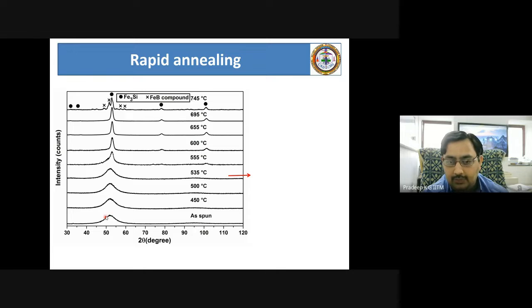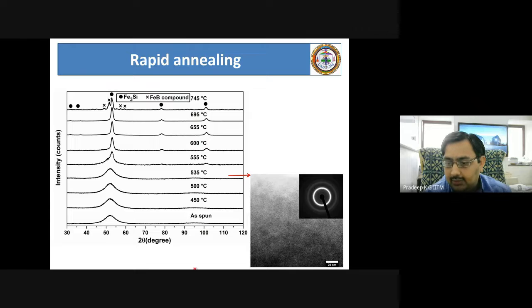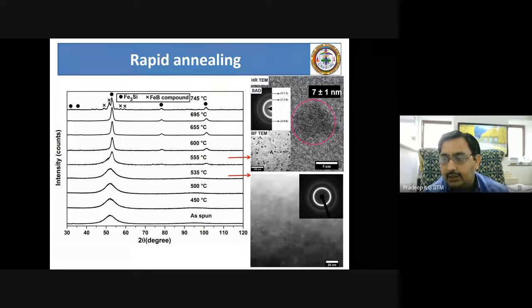That means if you now remember this 535-degree annealing, XRD says everything is in a random, or everything is in an amorphous state. You look at the electron microscopy image. This is a transmission electron microscopy image where there is no nanometer scale feature visible, and the diffraction pattern shows everything is amorphous. If you look at the 555 degrees X-ray diffraction, you can see there is a hint of iron 3 silicon formation. If you look at it in TEM, you see a lot of these nanocrystalline grains that are formed, but the microstructure at high resolution looks like a composite microstructure.